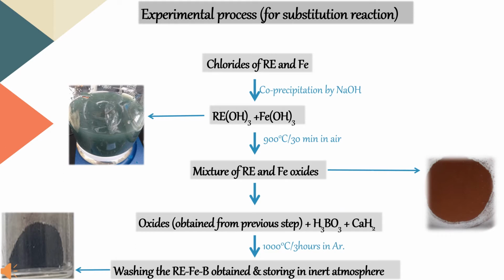So here is the experimental process for the substitution reactions. The reaction starts with the chlorides of Re and Fe. Re is the rare earth elements, and in my experiments they can be different lanthanides like Nd, Dy, Tb, Gd, Pr, Eu, or some other rare earth elements. I tried quite a few. In the first step, the different rare earth chlorides are converted to rare earth hydroxide and iron hydroxide by the co-precipitation process.